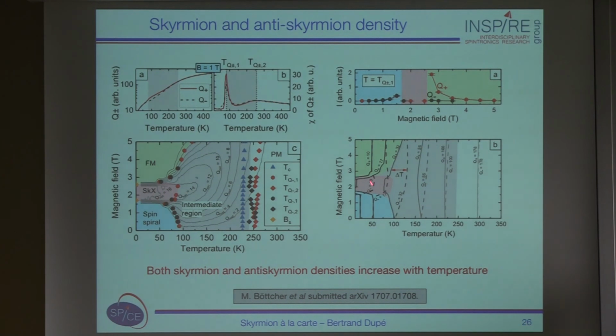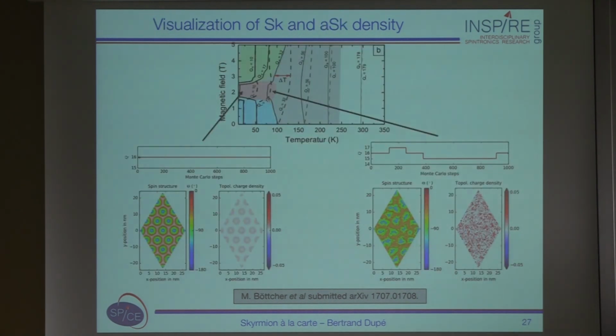So you see that at low temperature, unless you are in the skyrmion lattice phase, the Q plus and Q minus are on top of each other. They start to split when you go into this gray region, and then they are on top of each other again. Which means that when creating or deleting topological charge, it seems you create more skyrmions than anti-skyrmions, and then you freeze them when you go back to low temperature. So in order to have an idea of what's going on, I show you here the topological charge density distribution at two different temperatures for B equal 2 Tesla.